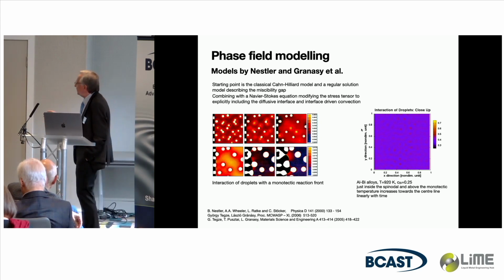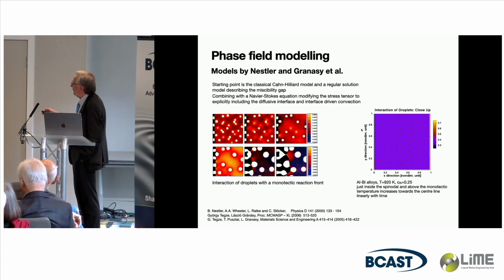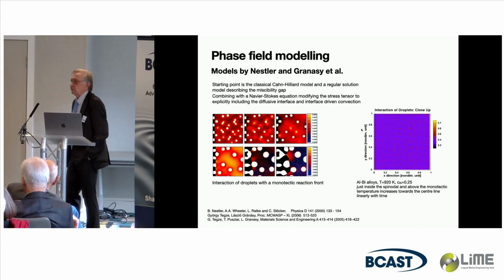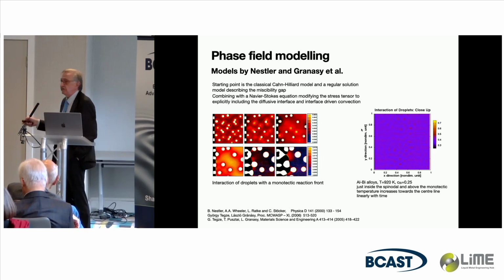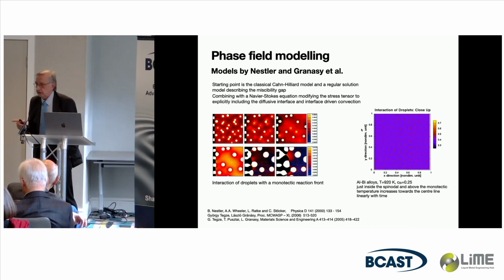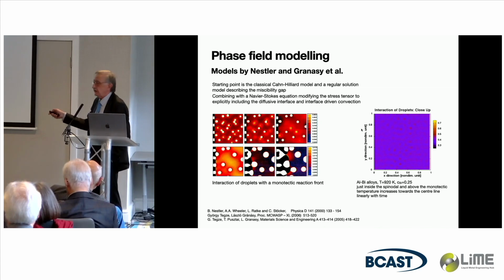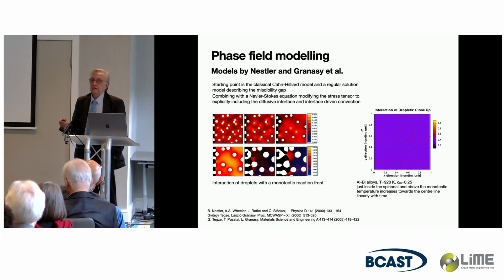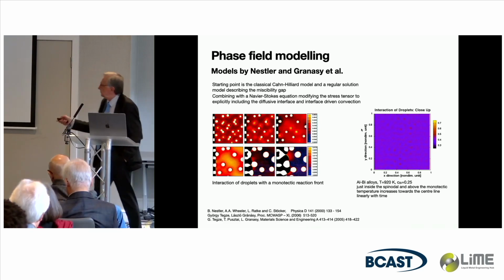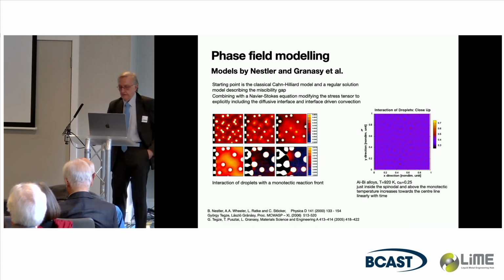One of the results of Britta was that indeed what you observe here is that in front of a monotectic reaction front, the droplets can coagulate, and they can even interact with the monotectic reaction front and perturb it so that it's not a planar interface. This is an artificial monotectic, and it's an artificial phase diagram, because typically in monotectic reactions, the liquid phase has a volume content of around 1 to 3-4%, but not to the extent as here.